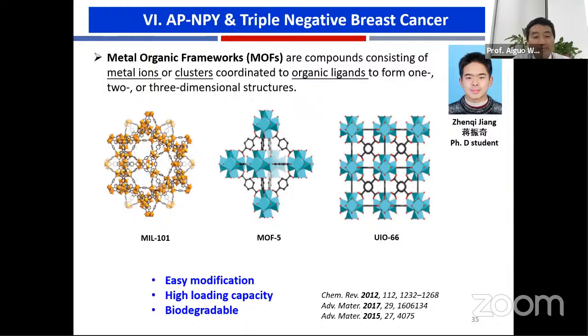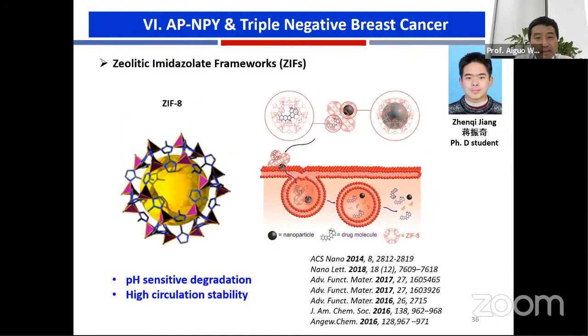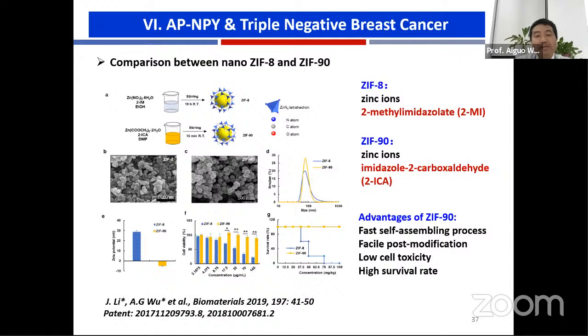And also, for example, different MOFs, with easy modification and high loading capacities. And also it is biodegradable. And for this one, we can show, for example, this MOF with pH sensitivity degradation and also with high circulation stabilities. So here we choose 2 kinds of MOFs, for example, ZIF8 and ZIF-90. And we found that ZIF-90 has a faster self-assembling process and also facile post-modification and with lower cell toxicity and high survival rate.